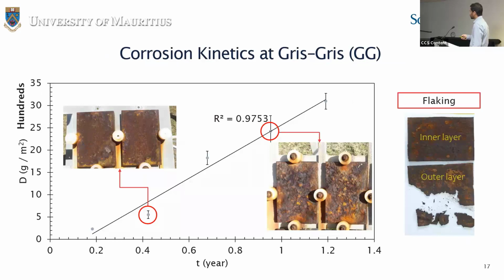This graph shows the total attack against time for the extreme marine site. This one shows a linear behavior of total attack against time. This has occurred because of exfoliation of the corroded plates at this site. You have the outer layer which comes off and the inner layer exposed. That's why corrosion persists at a linear rate at this site.